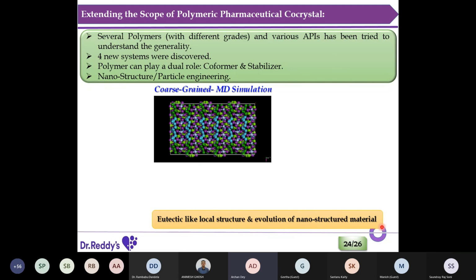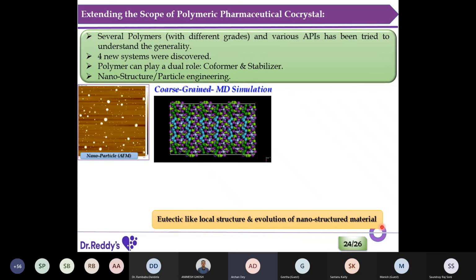This polymer now starts to play a dual role. It's not only a co-former, it's a stabilizer for nanostructures and nanoparticle engineering. So see the AFM image of one of these materials. We can control the material as nanomaterials, and the distribution is also quite good. And what is happening nicely, if you see the 100 to 400 nanometer particles, there is a core-shell. The core is the crystalline material and the shell is the polymer. In that way they get stabilized.